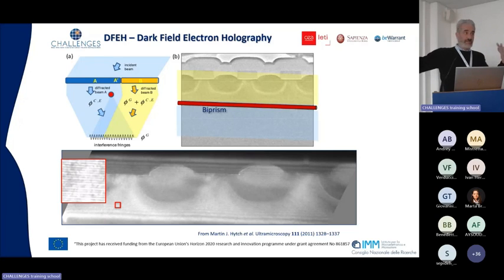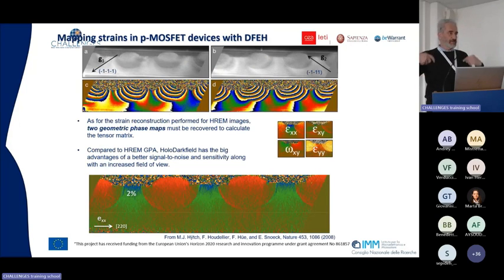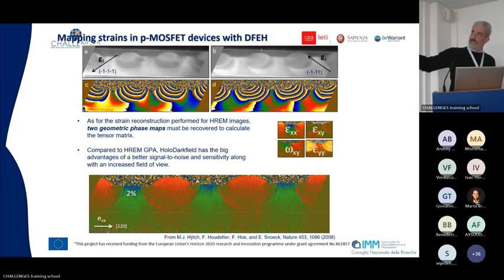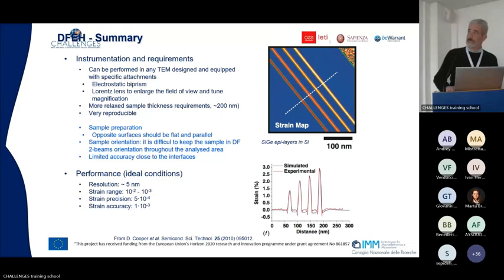These are the fringes arising from the holography. And by performing the analysis we did before, Fourier transform, filtering, inverse Fourier transform, you can end up with the map of the phase variation due to strain in our material. And then by using different reflections, perform a strain map of our material. Again, a very fascinating technique, and you can do it in almost any microscope, but you need an electron biprism.